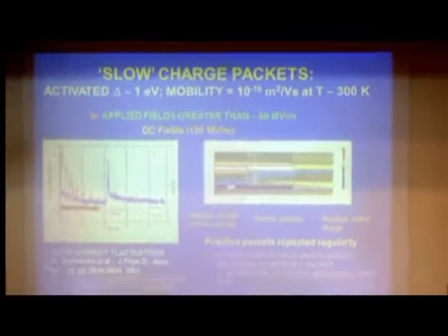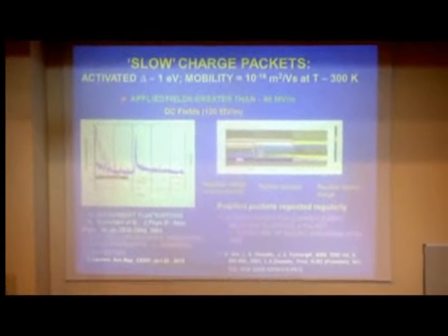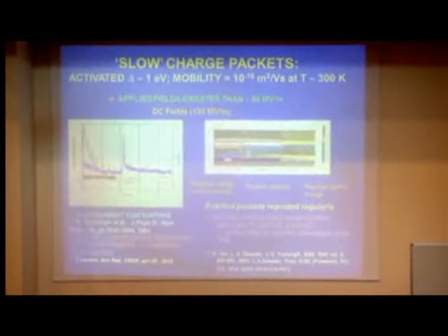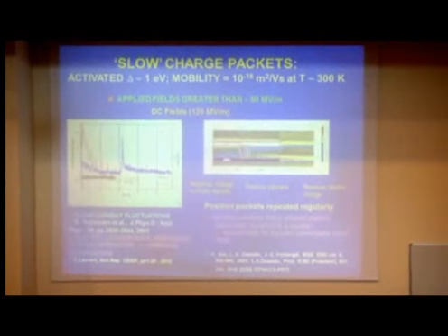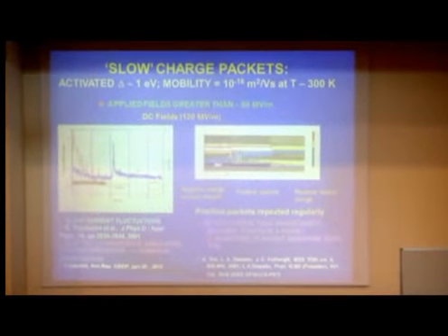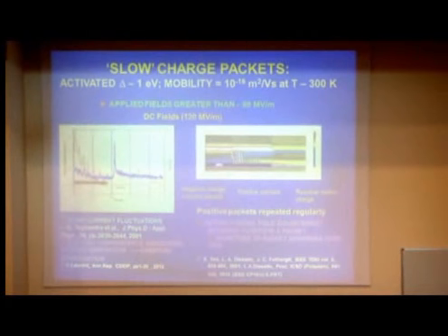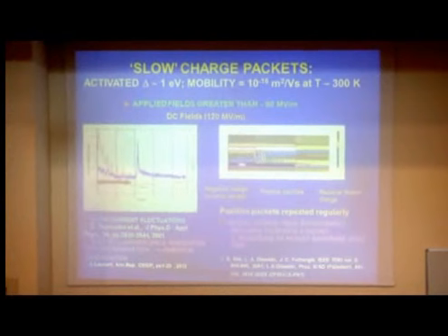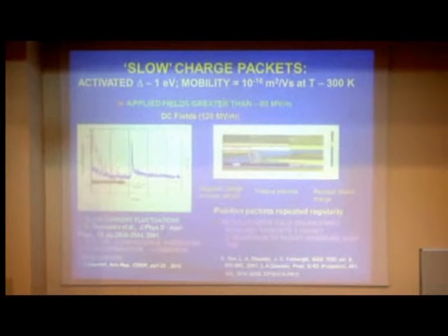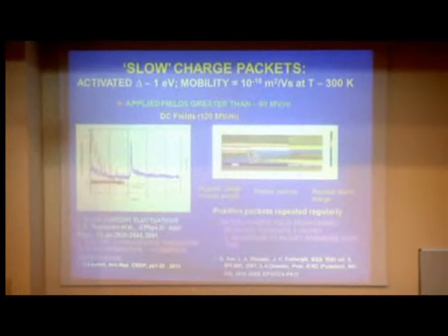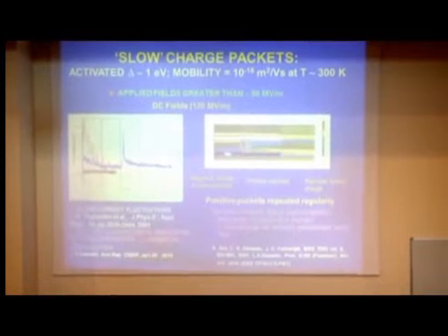We did some clever measurements, altering the voltage to see when the packets would stop moving and so on, and we were never able to get this field back up to 140, and we didn't get any more packets. But we could take another sample, apply the same 120 megavolts per meter field, and get exactly the same result. In this case, the packet amplitude diminishes over time. It goes up very substantially between number 1 and number 2, but it slowly dies off.